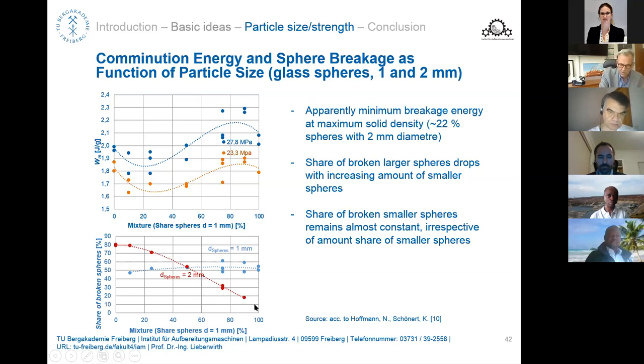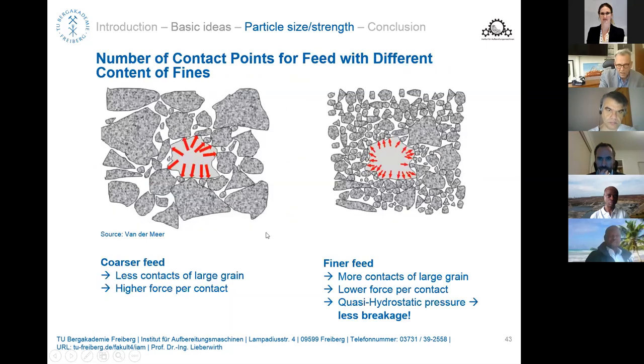This is very typical to what we have seen in the theory, that the coarser particles are supported by the finer particles during compaction in the confined bed comminution. So this is the explanation behind. For the coarse particles, you have a very limited number of contact points. The forces are larger, resulting in an increased comminution. While if you have many fine contacts, the large particle is protected. So the forces are lower.